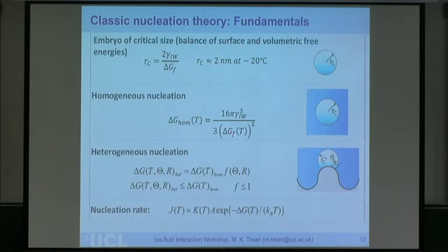If you plug this radius into calculating the total energy required, we get this sort of a number where we have, of course, the free energy change and the surface energy. So that's for homogeneous nucleation. For heterogeneous nucleation, we get a factor because the ice nucleus has to form on this solid object here, and it forms a contact angle, theta IW, and that comes in terms of this factor. And this factor, as we would expect thermodynamically again, is less than 1. And that's why heterogeneous nucleation is much more probable compared to homogeneous nucleation.